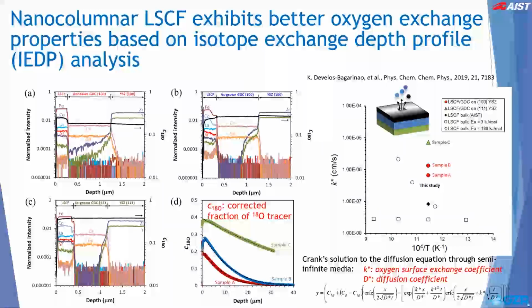From a fitting of the 18O profile using the Crank solution to the diffusion equation shown on the right, we can then obtain the oxygen surface exchange coefficient, denoted as K star, as well as the diffusion coefficient, denoted as D star. What we found out is that the apparent K star is much higher for the thin film samples compared to typical LSCF bulk. And it is higher by at least one order of magnitude for the film with dominantly 110 orientation compared to the film with dominantly 100 orientation. This drastic improvement is attributed to the comparatively higher catalytic activity of the 110 surface.